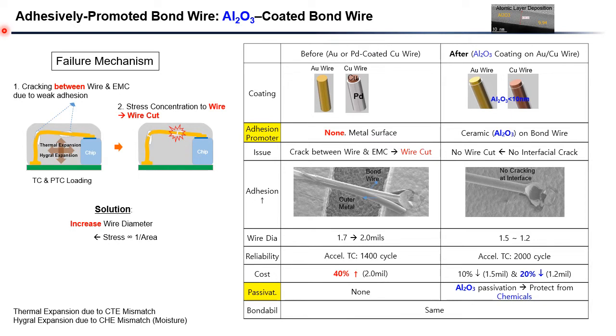First, aluminum oxide coating on bond wire for adhesion promoter. On your left-hand side, wire cut is one of the typical failure mechanisms in harsh environment. Because of CTE mismatch stresses, debonding occurs between wires and EMC. This is an interfacial fracture between the wires and EMC. These interfacial cracks grow long enough and then a wire cut occurs because the wire alone has to carry all of the thermal stresses without help of EMC. Typical solution is to increase the wire diameter because the bigger wire can carry a bigger stress.